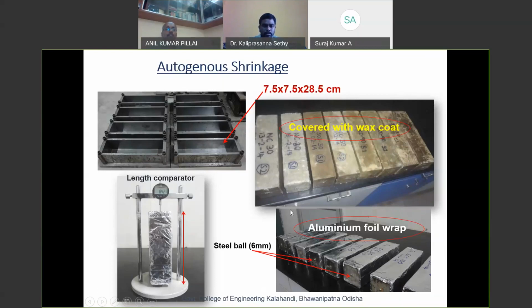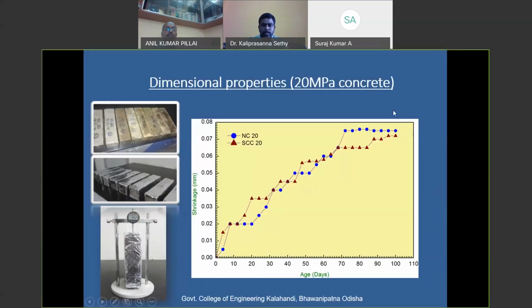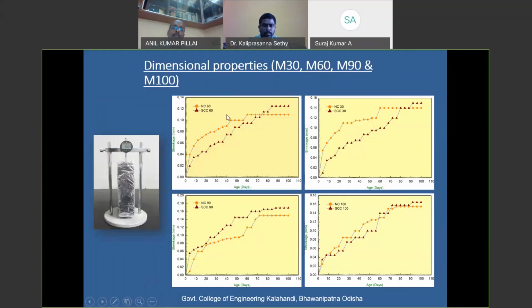And we have taken the readings up to 100 days, and from this you can see for M20 MPa concrete we are achieving a shrinkage value of maximum up to 0.07 mm, and for others maximum 0.12.